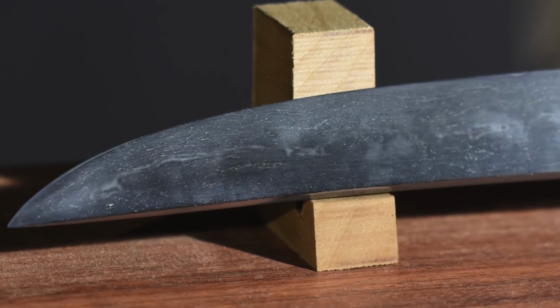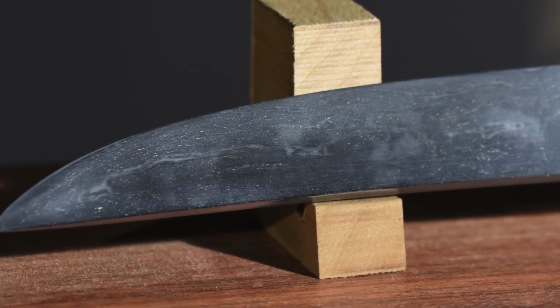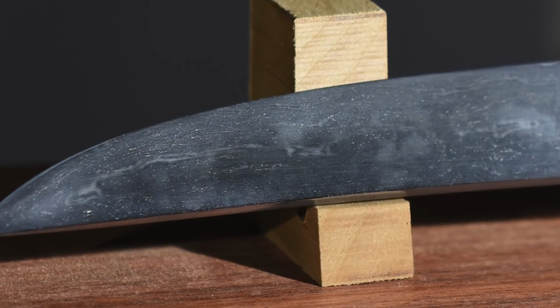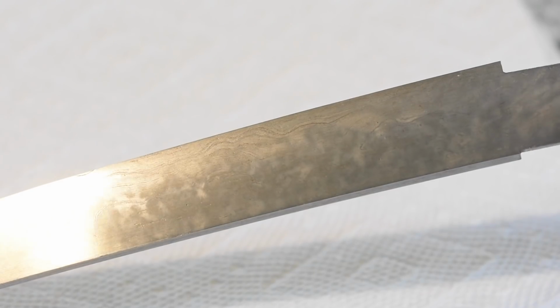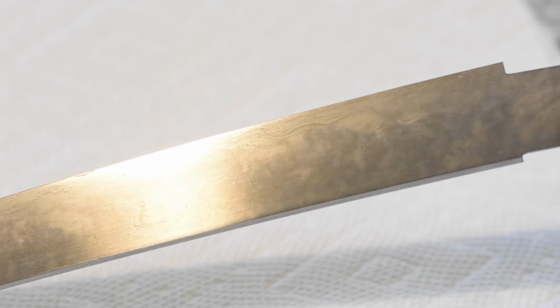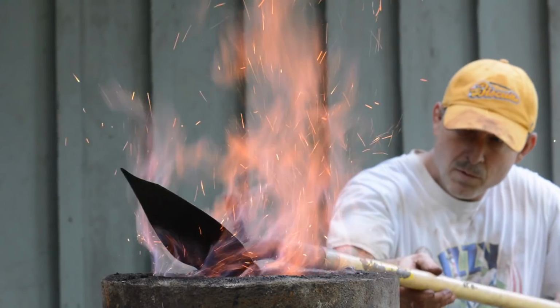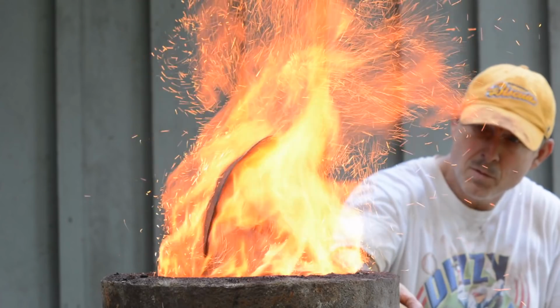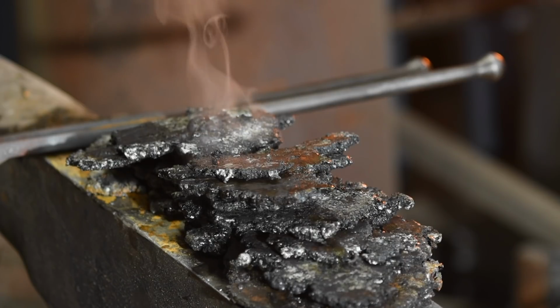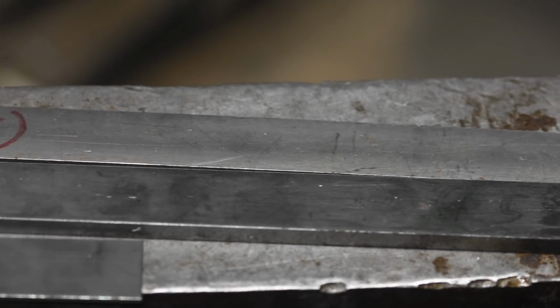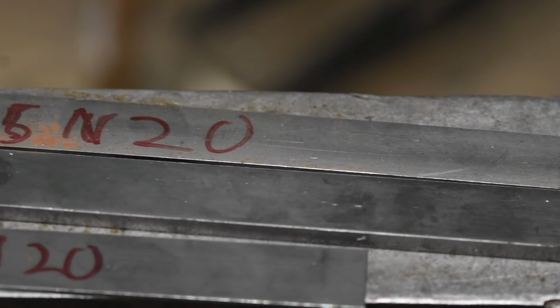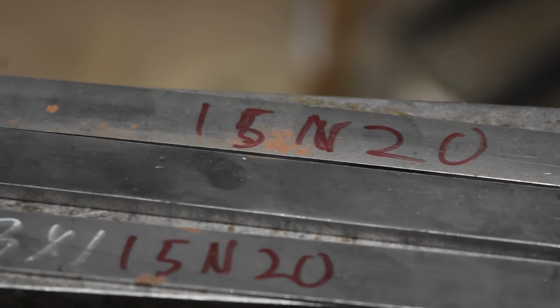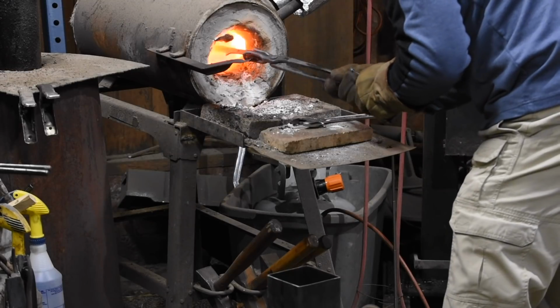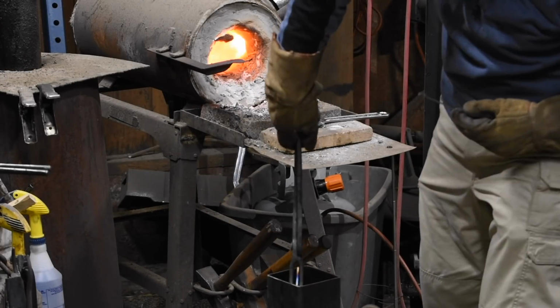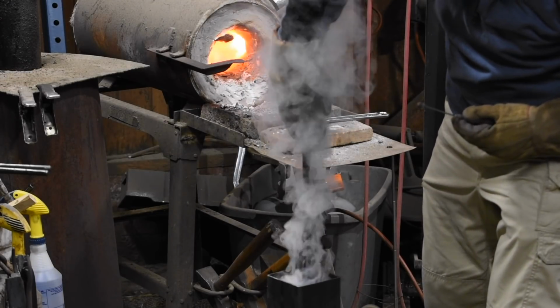Not the case here. The interesting thing about this blade is that it was water quenched without one shred of clay. So why did it form a hamon at all? Well, first, you have to understand that traditionally made Tamahagane has 0 manganese. Virtually all modern steels contain manganese, and manganese promotes hardening, so that sort of shifts the hardenability over a little bit and makes all modern steels more hardenable than a traditional Tamahagane-based steel.